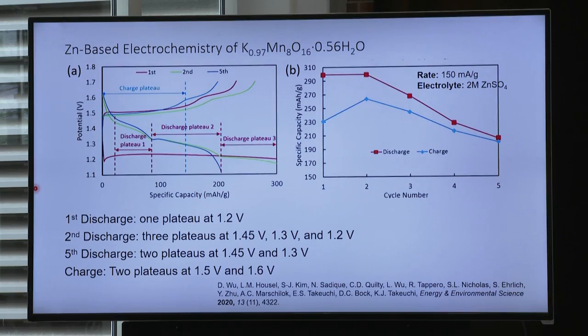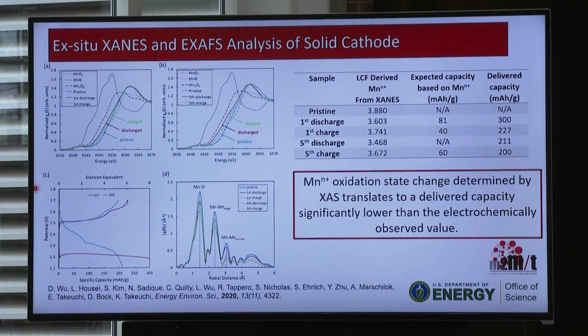Next thing was starting the electrochemistry, and we observed that the electrochemistry is quite different in cycle one and subsequent cycles. So we isolated samples of the electrodes after charge and discharge, and we did X-ray absorption studies. If you remember, I mentioned before, X-ray absorption is very useful in determining oxidation state of transition metals. So we determined the oxidation state of the manganese oxide in the charged and discharged condition, and then tried to relate it to the electrochemistry.